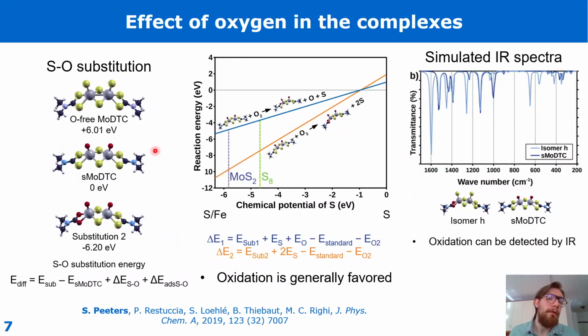To better understand the effect of oxygen in this compound, we can vary the number of oxygen atoms. And in fact, molecular structures with fewer oxygen atoms and more sulfur are less stable than the ones with more oxygen atoms. So this calculation relies on the fact that sulfur and oxygen are exchanged on a metallic substrate.